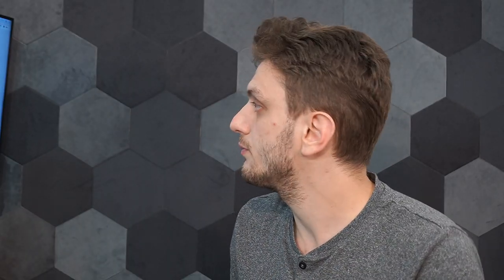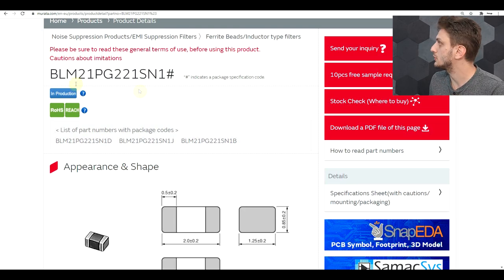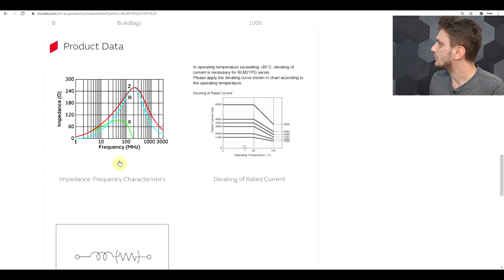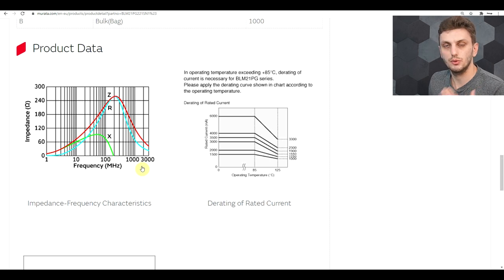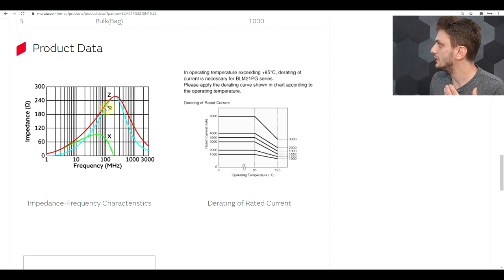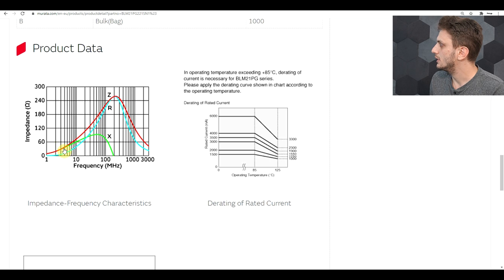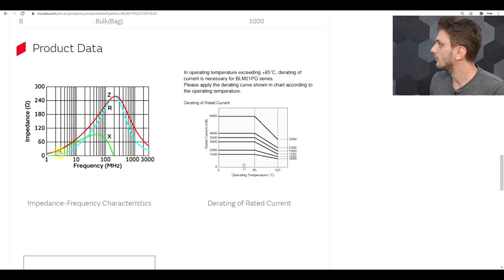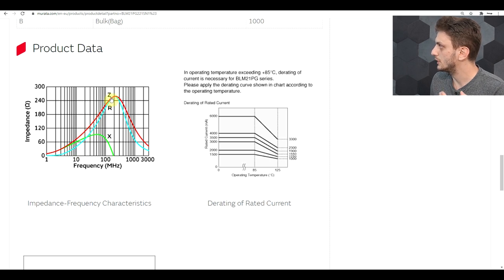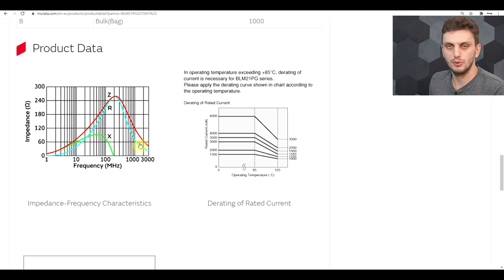One more thing I want to show you is a ferrite data sheet. So what I have here is a ferrite data sheet from the manufacturer Murata, and one of the informations present on this page is this impedance graph, where we have a highlight of total impedance, resistive behavior, and reactance. And here we can see, just like with our iron core, at low frequencies impedance is predominantly reactive, caused by inductance. Afterwards it becomes predominantly resistive with a peak impedance. And finally, resistance will drop and the capacitive component kicks in. Now depending on how you build your inductor, you will have these three distinct regions, so inductive, resistive, and capacitive. Or if you have too many turns and too much capacity, then the resistive behavior will be very very small or even non-existent, so you will go directly from the inductive behavior to the capacitive behavior.